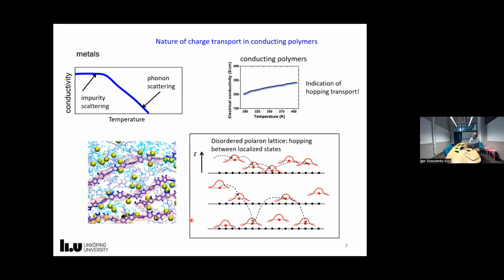So therefore, we can expect hopping type of conductance in conducting polymers. And indeed it is the case. So this is just a reminder. This is what you expect from a metal: conductivity decreases with the temperature. But a typical experiment for conductivity in a polymer shows you an increase of electronic conductivity with the temperature. And as we discussed, this is an indication of hopping transport.